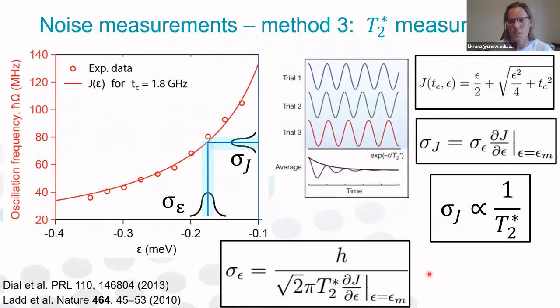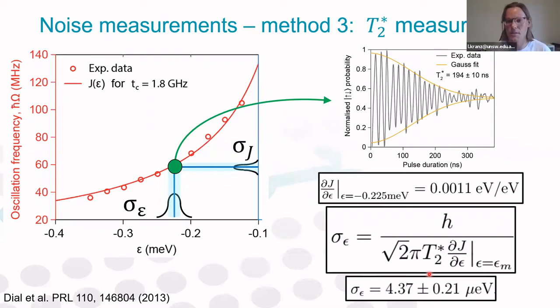And this is great. Now we can use this method to calculate sigma epsilon in our device. So for the data I showed you previously, the T2 star time was around 200 nanoseconds, and I know the detuning at which this data was taken, and therefore I can calculate dJ/dε at this position, and I can plug all of these values into my master equation, and I'm getting something like 4.4 micro eV of detuning oscillations. And this is in absolute energy scale, micro eV. So you might think it's a good measure of charge noise in your device. And actually, yeah, this is something that people report for different devices. But actually, as I'm going to show you now, it's not really that good a metric.